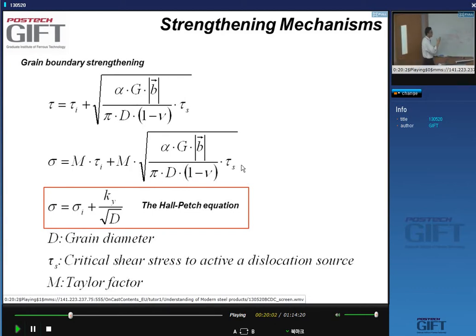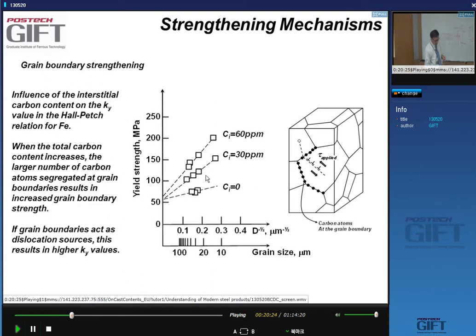There are other theories that say the effect you get is actually related to the grain boundaries, and that as you have this very high stress accumulation at the grain boundary, there comes a moment where the grain boundary starts emitting dislocations. The reason why these alternative theories have been proposed, and why we mention it here, is because they appear to apply for steels. If you look at the Hall-Petch equation, you measure yield strengths in samples with different grain sizes, and that is very simple.